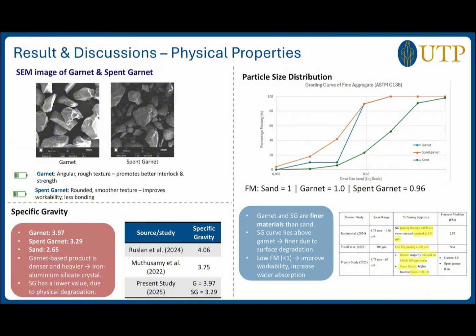The first one is we discuss on the physical properties. For physical properties, we conduct 3 tests, and the first one is SEM analysis. So based on this picture here, we can see garnet has angular, rough texture, which can promote better interlock and strength. And for the spent garnet, it has rounded and smoother texture, which can improve workability, but it will give less bonding. And for specific gravity, we can see from the result here, garnet and spent garnet have higher specific gravity compared to sand. It is because garnet-based product consists of iron aluminum silicate crystal, which contribute to its denser and heaviness.